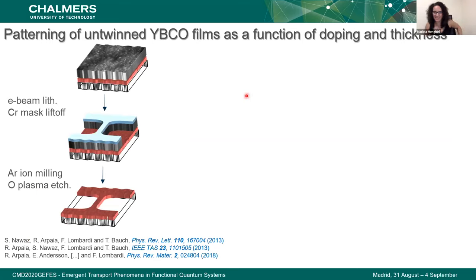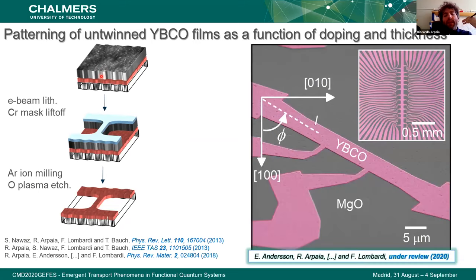And then we pattern this film by using a technique that we have improved, using a Cr mask in combination with electron beam lithography and argon ion milling. And basically, by doing so, we can get structures that are unaffected by the patterning, preserving pristine YBCO properties. And we pattern now these microbars as a function of the in-plane axis of the substrate.